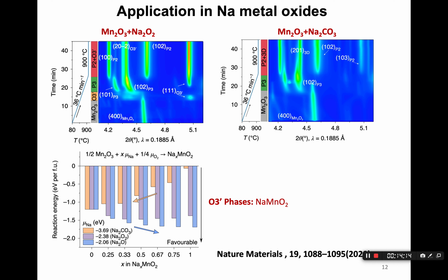When we calculate the reaction energy as a function of different precursors, we have 3 bars here. The yellow bar demonstrates what happens if we use sodium carbonate, corresponding to a lower chemical potential, while the purple bar demonstrates sodium peroxide, which has a slightly higher chemical potential of sodium. And we can go to the most stable sodium precursor, which is sodium oxide. So from sodium carbonate to sodium oxide, we are pushing up the chemical potential of sodium. As a consequence, we are also pushing up the sodium content in the sodium metal oxide. This gives you a flavor that if you raise the chemical potential of sodium, it's more likely for sodium to incorporate into the metal oxide framework. That is why you tend to form a high sodium content compound.